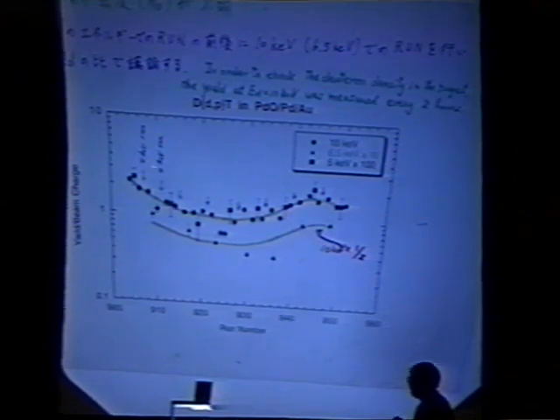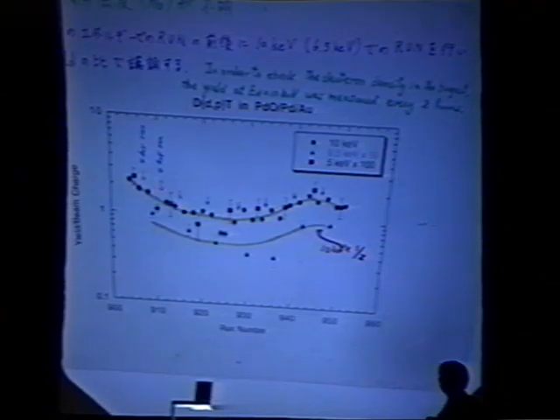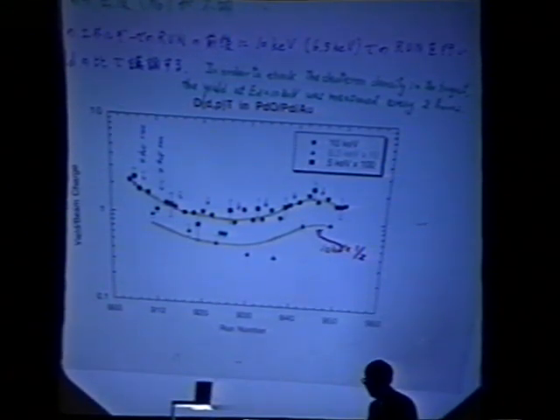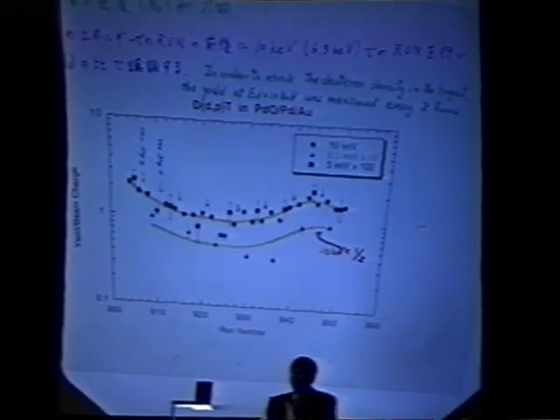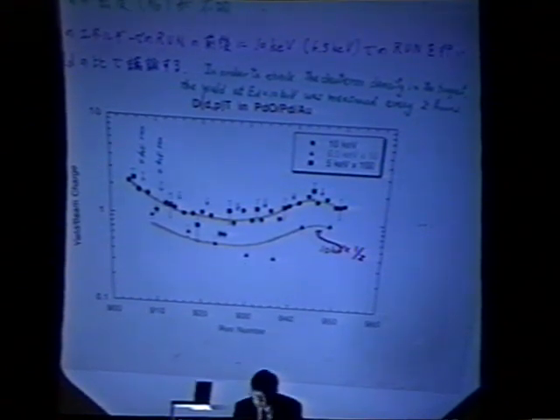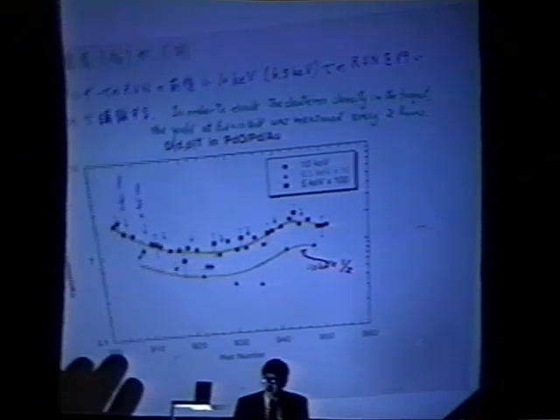In this case, we bombarded at 5 keV for example, for 2 hours. Then after 2 hours, we switch to 10 keV again. Then we got this one. If you look at, for example, the 5 keV data, this trend of the yield just follows the yields at 10 keV. So after that, we always normalize to the 10 keV. In that sense, what we measure is just a normalized thick target yield, not absolute.